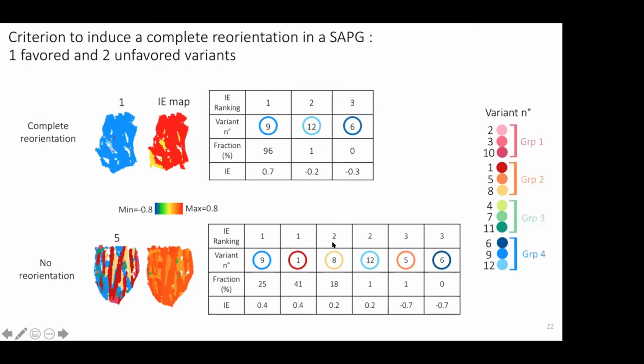Thanks to that, we can build some criteria. The general one is to have reorientation between two variants. You just need one favored and one unfavored, and the one which is favored will grow at the expense of the others. But to have a more specific criterion, at the scale of a self-accommodating group, you need to have one variant which is favored and two that are unfavored.